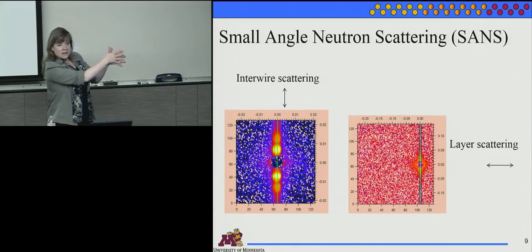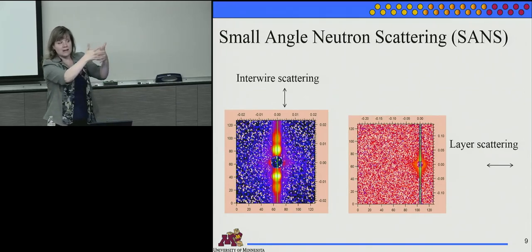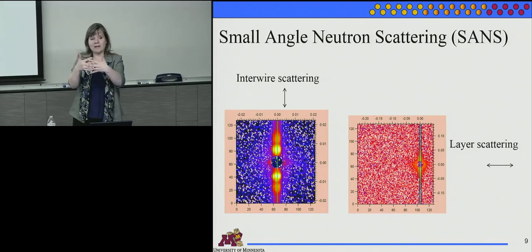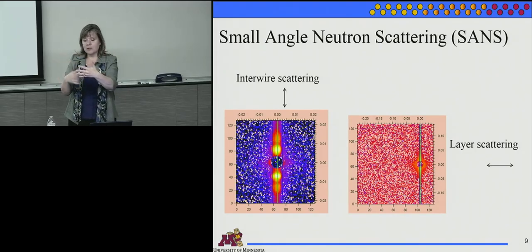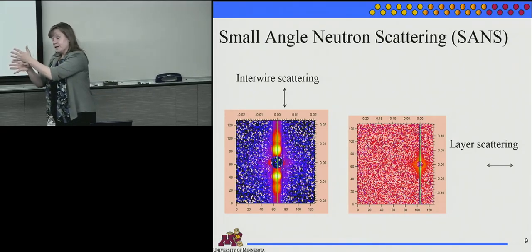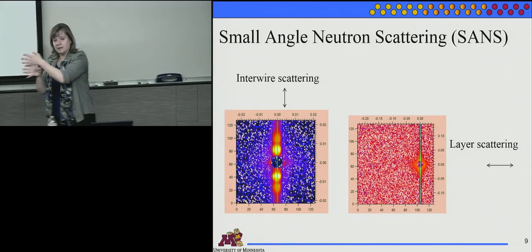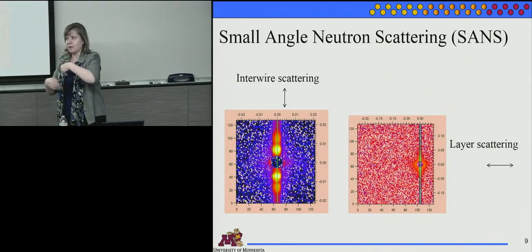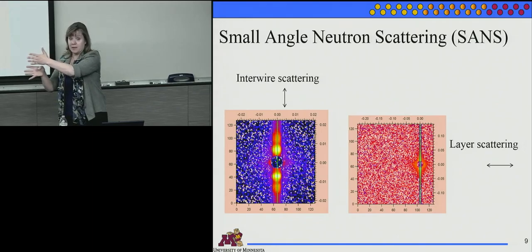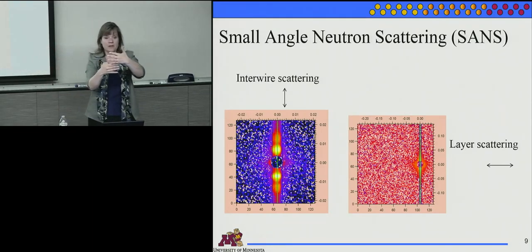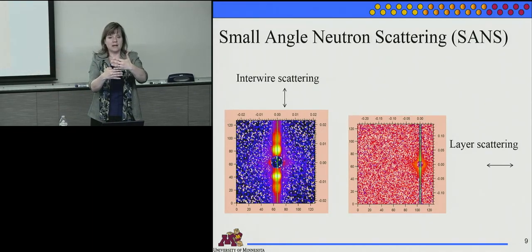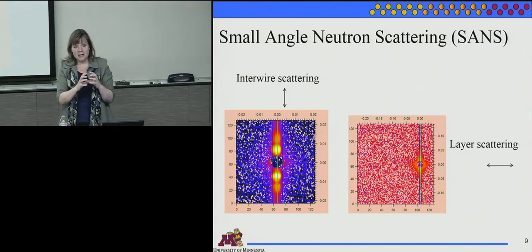You magnetize it that way, they're all ferromagnetic again, and so on. But it turns out in this state, what we're seeing with the neutrons is instead the pancakes do all, if you apply a strong enough field, all the cobalt follows the shape anisotropy, plus basically they're just magnetized by the field. But when you come back to zero field, there's actually domains of pancakes that stay magnetized together, and that forms an isotropic shape, which seems to make sense for some energetics also.